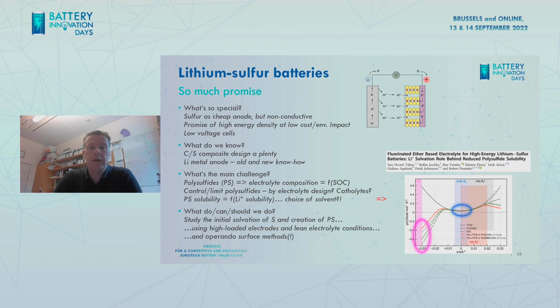There are some interesting notions now where you have electrolytes that preferentially solvate the lithium cations and not polysulfides, and that's an interesting route, and we'll see some of that coming out this year. What I think we should do, that's very much basic studies. Study really the initial solvation of the sulfur and creation of polysulfides at the very surface of the electrode. And you would have to do that using very highly loaded electrodes and lean electrolyte conditions, because it's something about your solubility here. So you need to have both of those factors in the correct state.